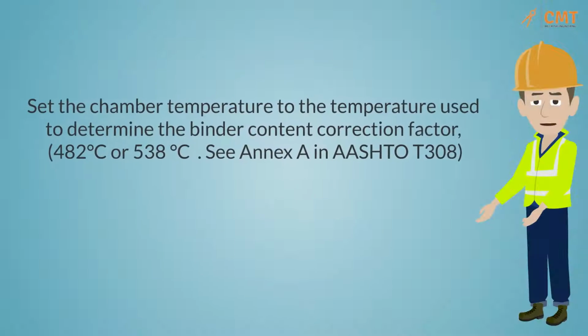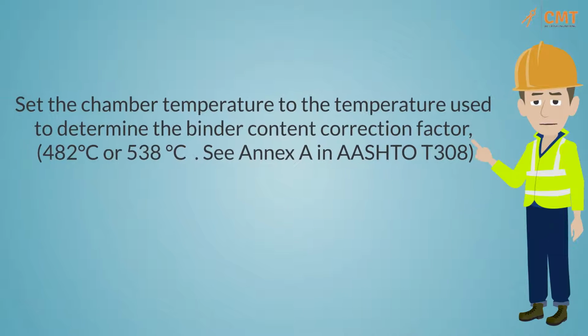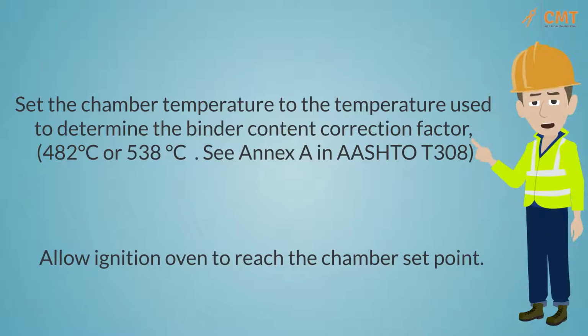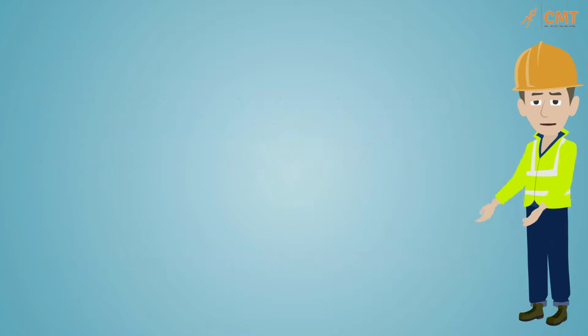To start this test, you will need to turn on the ignition oven and set the chamber temperature to the temperature used to determine the binder content correction factor, which is either 482 degrees or 538 degrees Celsius. See Annex A in AASHTO T308. Then you will need to allow approximately 3 hours for the ignition oven to reach the chamber set point.